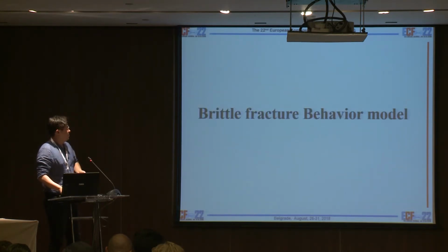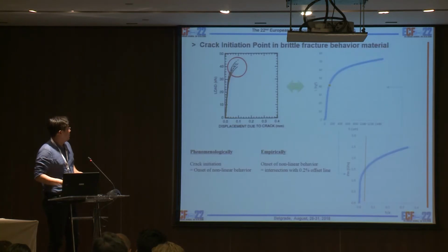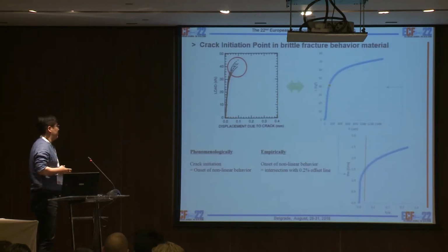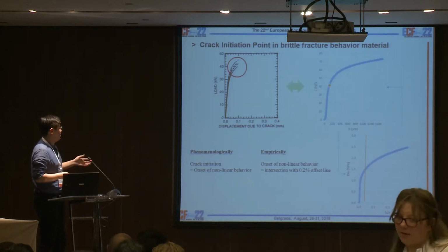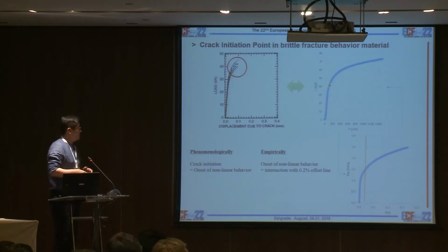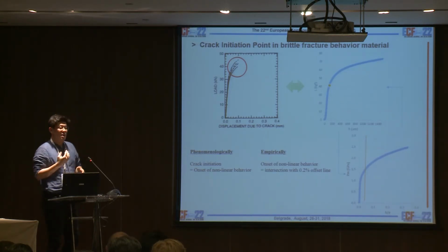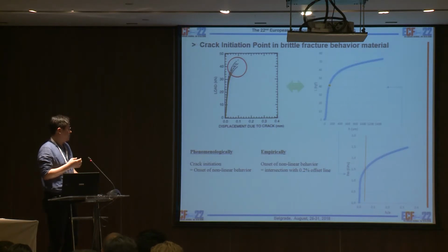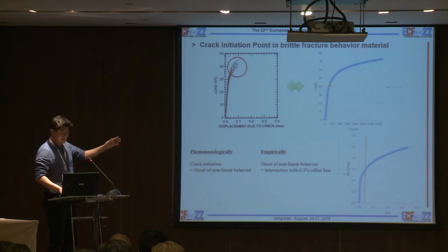And the brittle fracture model is simpler. We approach this model as a testing phenomenon. In the cracked round bar test, for materials with relatively low fracture toughness, the crack initiation point is the onset of nonlinear behavior. So at this point, we approached it from an engineering point of view. We used the 0.2% offset line like a tensile test. So we found the crack initiation point at the intersection of the two lines.